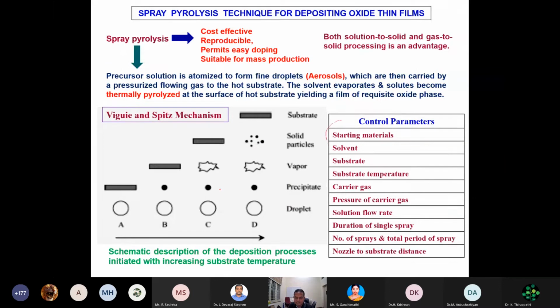You can see these are all the control parameters which are associated with the spray pyrolysis technique. The starting material is important because it should have a low decomposition point, and the solvent which you are putting is also very important. And then the substrate which you are using, substrate temperature, carrier gas, and the pressure of the gas which you are using to create vapors or the aerosol of this particular solution.